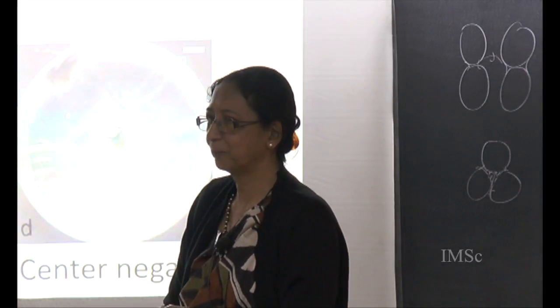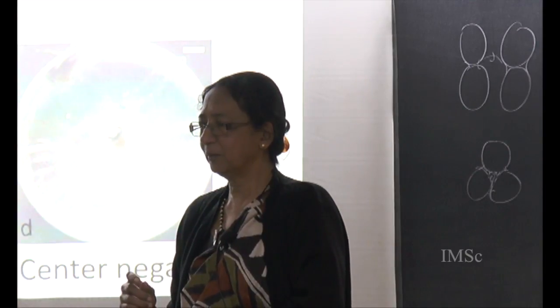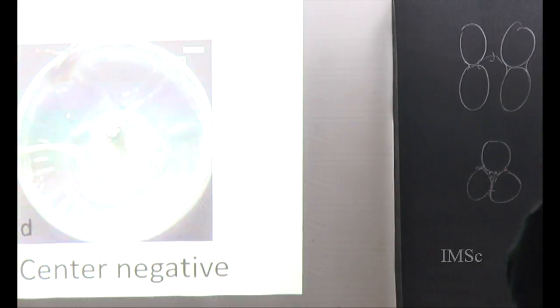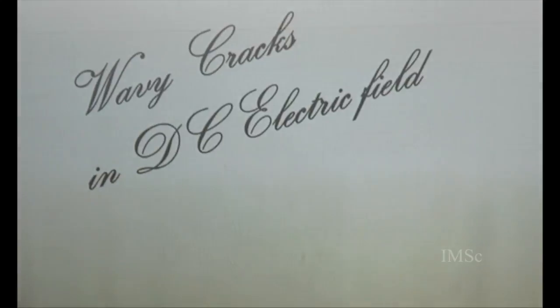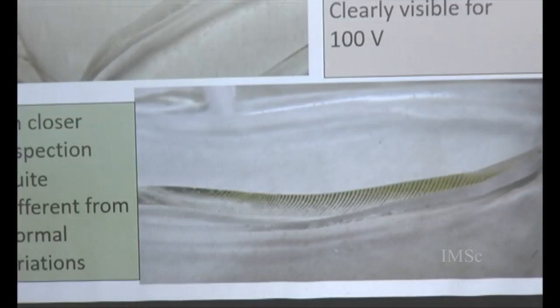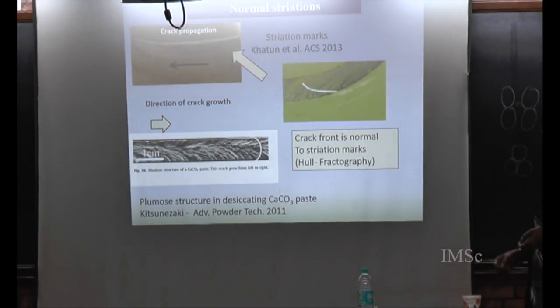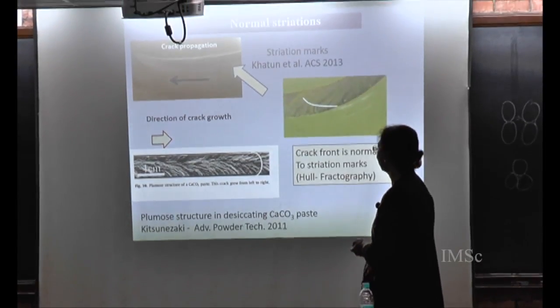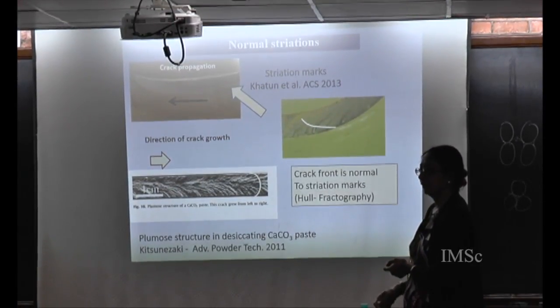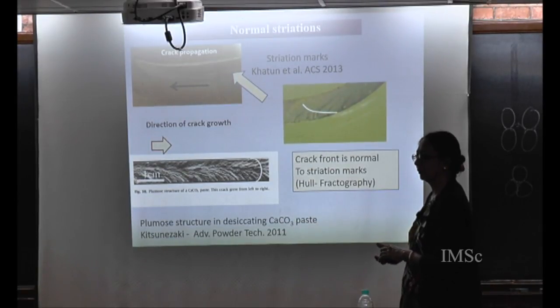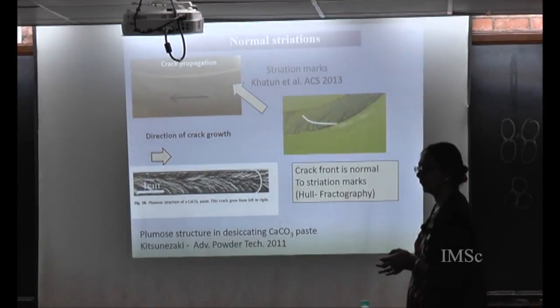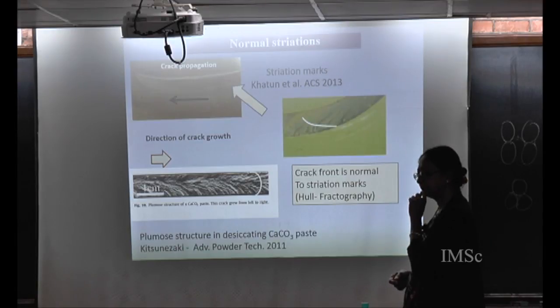So I was just wondering in your system if the crests that you see correspond to periods where your rupture front is pinned, and then it accelerates and deviates, and whether your crests are correlated with the crack front speed. Probably that would be what I was referring to as the usual type of striation marks. This one? No. The white lines. You were showing some other Perspex things where the lines corresponded to the crack fronts. What I'm talking about is a situation where the lines that remain on the PMMA plates correspond to some instantaneous positions of the front. And when the front doesn't go fast, there is a marked line that stays on the surface when it accelerates afterwards.